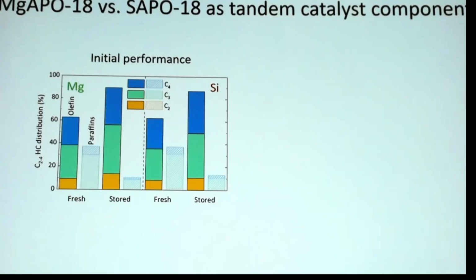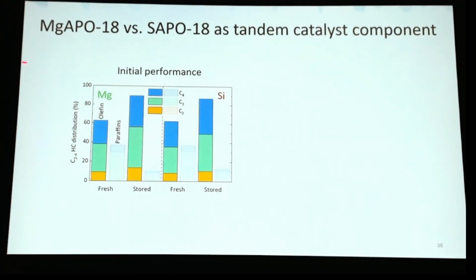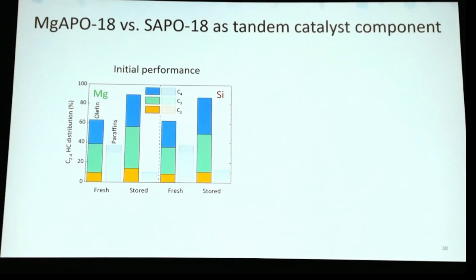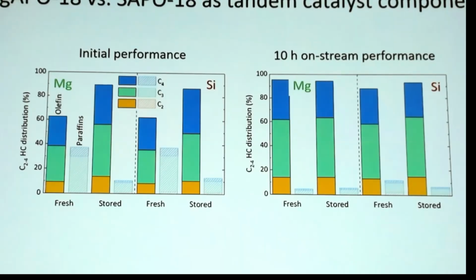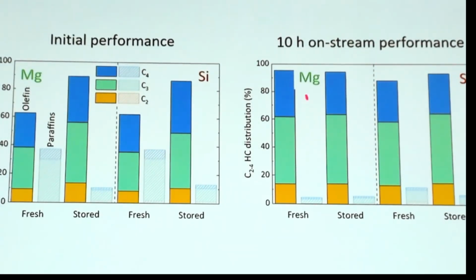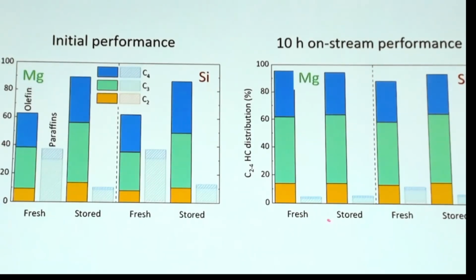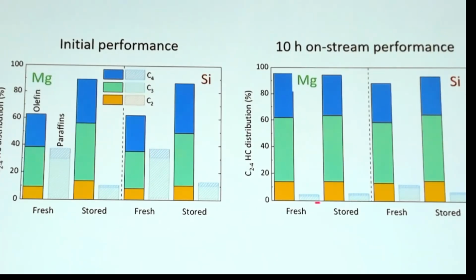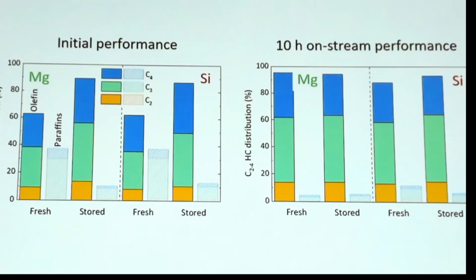Now, when we look at the initial performance of these materials, for the magnesium one, olefin and paraffin selectivity, we see that we have a higher paraffin selectivity in the magnesium material than we have in the SAPO, and it gets lower with time. But then, if we have in situ calcination of the material, and then after 10 hours on stream performance, we see that whether we have the fresh or in situ calcined or the stored ones, they perform similarly for magnesium and almost similarly also for silicon. And that means that the initial state of the material after storage is very similar to the deactivated state of the material after 10 hours on stream.